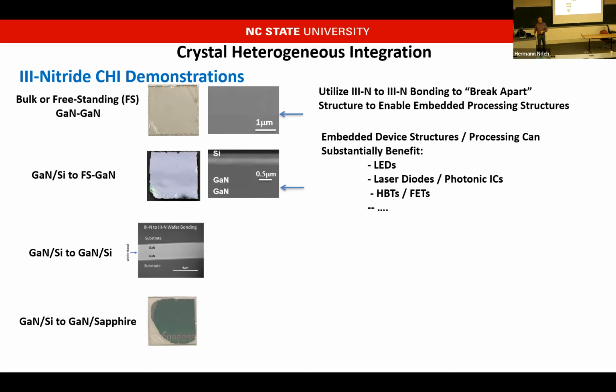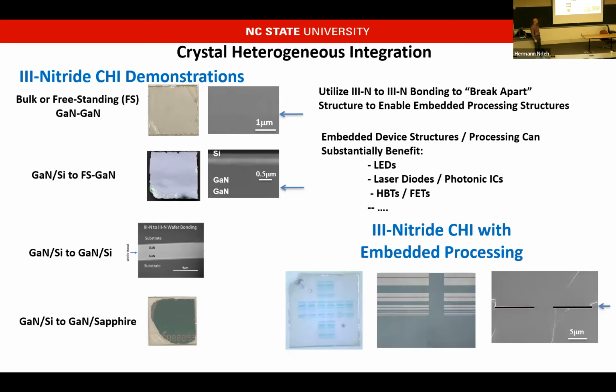So what does this enable us to do? In many cases, we like to embed certain things around an active region of a device, or two-dimensionally. It's really difficult to do that if we're processing everything from the surface in gallium nitride. So what we can do is take a device structure and stop at whatever point we want that processing to stop, then build another wafer with the other half, process the wafers, and put them together. So we can make embedded structures, and that really can benefit LEDs, lasers, HBTs. This is an example of some of what we're able to do. This is a patterned structure, and you can see a closer up view and even a cross section. The first work that we're doing here will be towards making passive waveguides with those embedded structures.